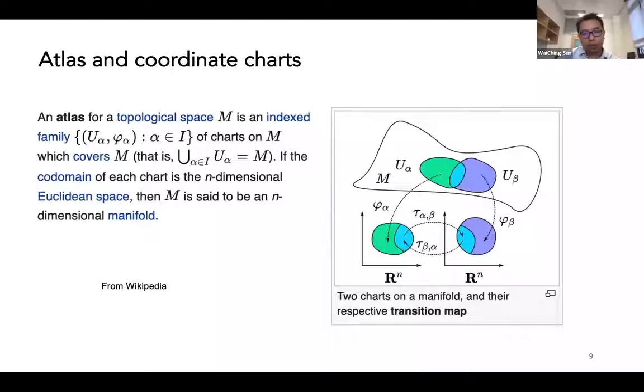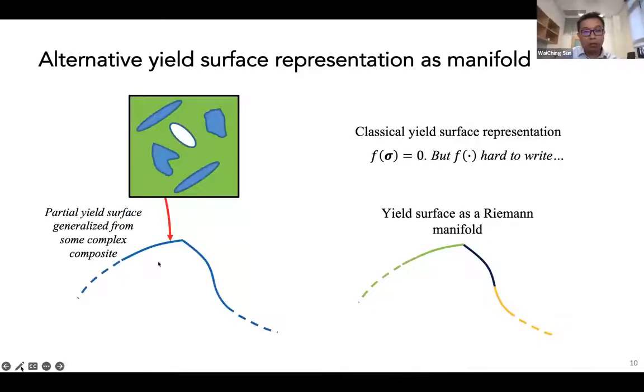Okay, so in particular, what we're trying to create are those local mappings that can allow us to describe the yielding, and then we want to connect them so that they form an atlas that is consistent with each other. And this would be the alternative approach to define the yield surface. What we actually want to show is whether this really complex approach is necessary or not, and if we use this, what is the benefit? In this particular case, what we want to answer is, if I change the microstructure, how would the corresponding yield surface change, and whether we can predict the evolution of those yield surfaces?